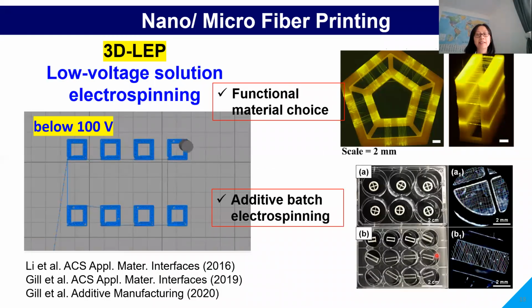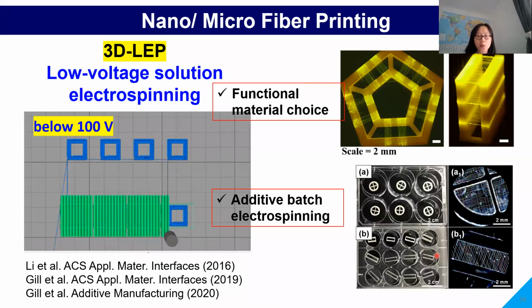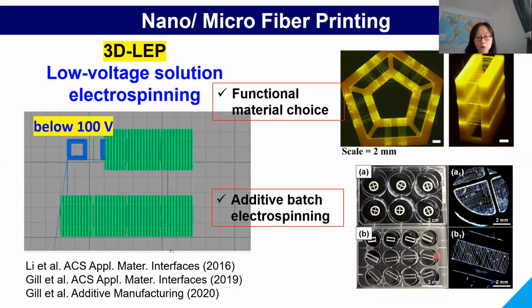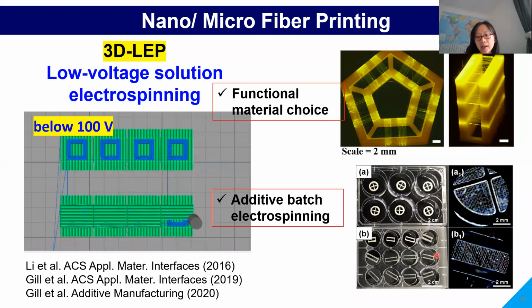So after I established my independent group in 2016, we developed a new process called low voltage electrospinning, which decreases the operation voltage from over kilovolts to about 100 volts. What I'm showing you here is that I combine low voltage electrospinning and 3D plastic printing. So we can start to design fiber patterns through a CAD file like conventional 3D printing. And this is a new process flow called additive batch electrospinning.